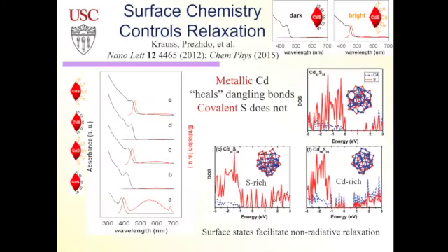So what we learned from all of this is that quantum dots, in fact all nanoscale materials, are not very clean. If you work with molecules, they're very well defined. And maybe if you make quantum dots epitaxially in vacuum, they're also very well defined. But if you make all those materials the chemistry way, which I'm a chemist, they're very dirty, not very well defined. And the simple particle in a box model that started nanotechnology, I would say, is too simplistic. So what we also learned in collaboration with Todd Krauss in Rochester is that the surfaces of quantum dots are not stoichiometric.